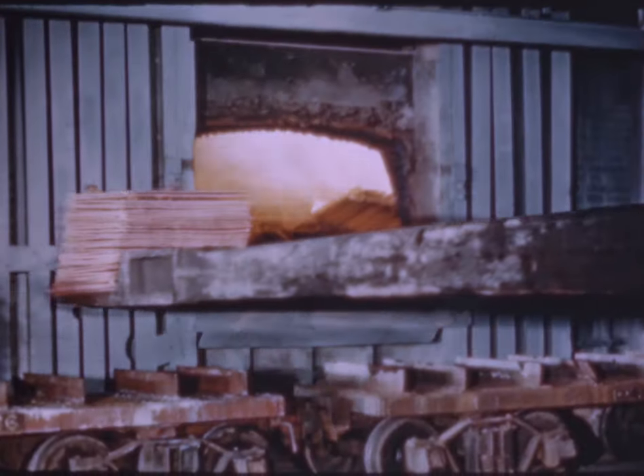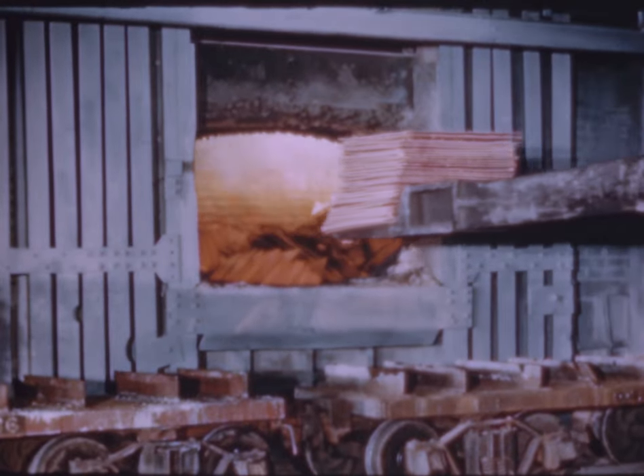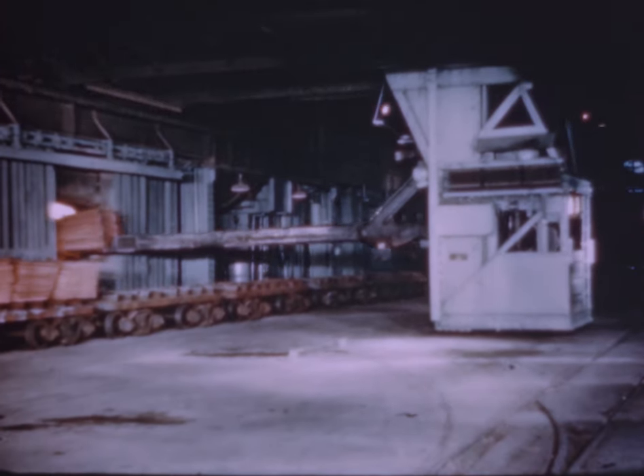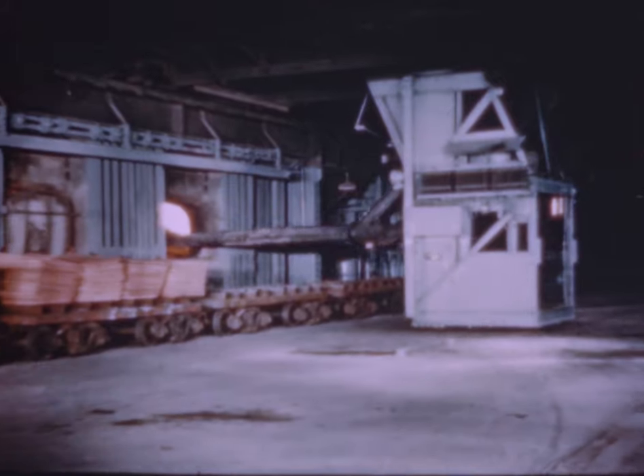The cathode copper is charged into these gas-fired furnaces, each with a casting wheel and auxiliary equipment, and each capable of treating more than 500,000 pounds of copper every day. It takes 16 hours to melt the charge, during which time the copper becomes somewhat oxidized, having absorbed some gaseous products of combustion, which must be eliminated before casting.